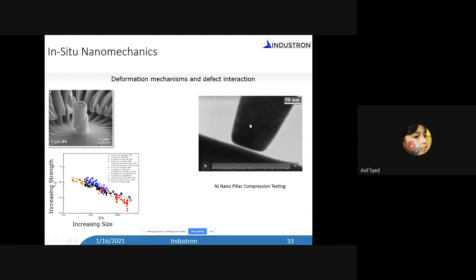So at that time, we were developing this instrumentation inside a transmission electron microscope. This particular experiment was done inside a transmission electron microscope. You can see the pillar over here, and underneath you see a flat indented tip. This material is being prepared by the FIB technique, a focused ion beam, and you kind of carve the pillar out. When you do that, you create defects, and these defects are the dark things that you can see on this pillar. Those are all dislocations that have been created when you carve this pillar.